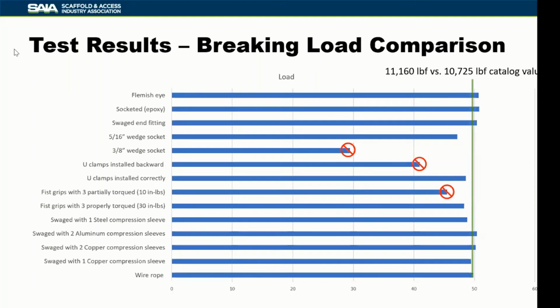Fist grips that are improperly torqued, you can see that having the proper torque on your fist grips is vitally important to those properly performing. They are published as having 80% of the strength of the wire rope, and they perform significantly better than that in our testing.